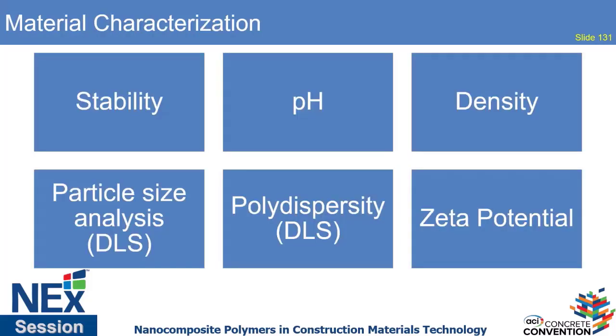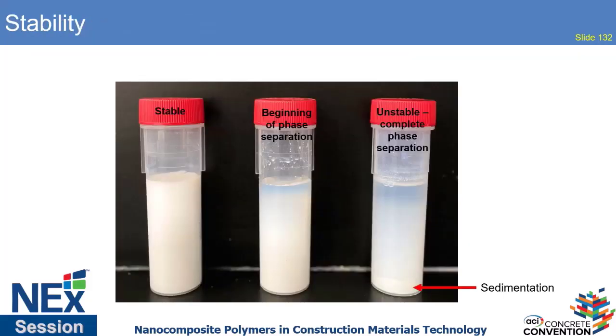Those are some of the material characterizations for the different formulations that we have done. The stability here is visual, and it's primarily for gravitational stability. The first tube is representative of samples that have been stable, and the majority of the formulations, with the exception of those that were not sonicated, have shown stability, as in the first tube. The second and the third tubes are representative of the samples that were not sonicated. Shortly after we were done with the mixing or homogenization, the phase separation started, and you get a complete phase separation or sedimentation.